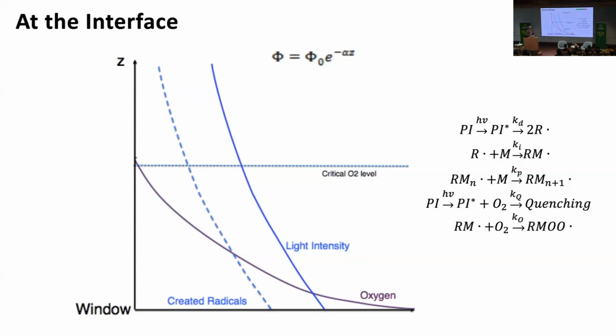I'm not going into too much detail, but you'll understand this. So this is a concentration axis here, going from the window up into the resin, in a Z direction. So let's walk through this. Light's coming through the window, and light is at its most intense as it exits the window. Now, the light intensity will decrease as a function of distance up into the liquid just due to the molar absorptivity of the resin, okay? That light is decomposing a photoinitiator. So that photoinitiator will decompose into radicals. So the radical concentration will basically follow the light intensity up as a function of distance.